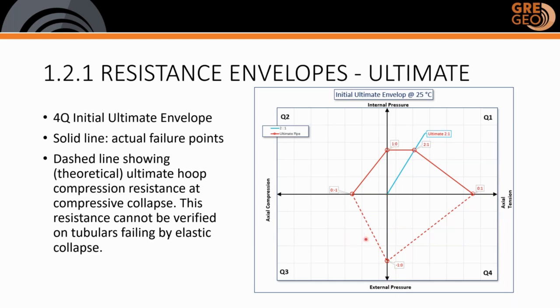The 2.1 point you see over here is found from internal pressure tests with cap end loads. The 1.0 point is from internal pressure without end cap loads. The 0.-1 point is from tests using actual compression tests. The 0.1 point is from actual tensile tests. And the -1.0 point is a calculated value for the theoretical compressive strength. That's why the lower part of the envelope is indicated by the dashed red line.